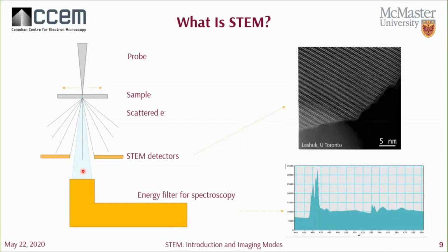at very high speeds and using a high acceleration voltage. So STEM most commonly uses detectors that collect forward scattered electrons to form an image, and almost always can be used in conjunction with some kind of spectroscopy technique, such as that shown in this image here, where we use an energy filter to collect some energy loss spectra. From all this, we can get the structure, the chemistry, and the bonding of your sample at very high spatial resolution.